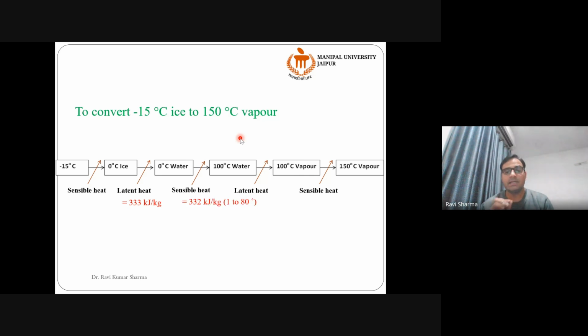Now, I have done a calculation for converting water from 1 degree centigrade to 80 degree centigrade, and the amount of heat required is 332 kilojoule per kg. So what you can see here, this latent heat is equal to this sensible heat.